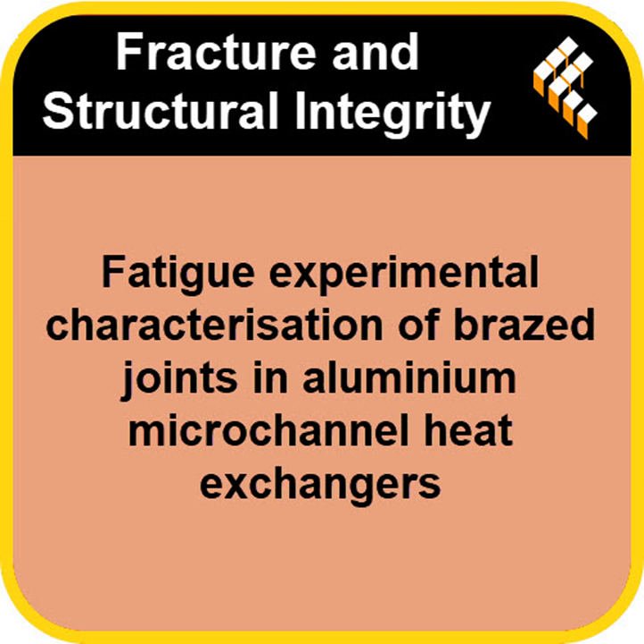And these flaws acted as the trigger points. That's a conclusion. They acted as preferential sites, like little ready-made defects, for the fatigue cracks to nucleate and start growing. The inclusion creates a local weak spot, maybe even its own microstress concentration, ensuring the crack starts there, probably long before the surrounding defect-free metal would have initiated a crack on its own. It's the ultimate trigger. Wow.